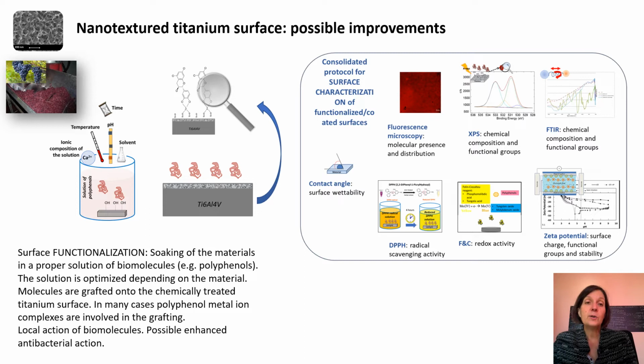And we can also have an improvement of the surface because thanks to the presence of the hydroxide groups, we can make a functionalization of the surface. So we can add some biomolecules. For instance, we tried with polyphenols extracted from black and white grapes. And polyphenols are auto-fluorescent, so you can see here a pretty nice coating of polyphenols on the surface.